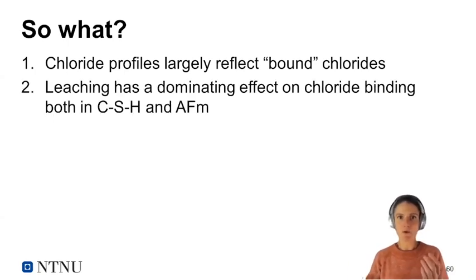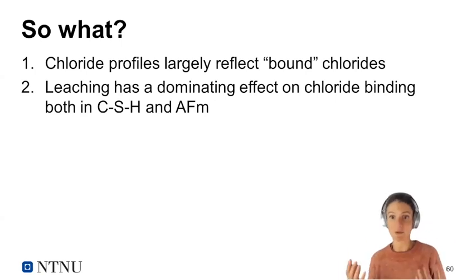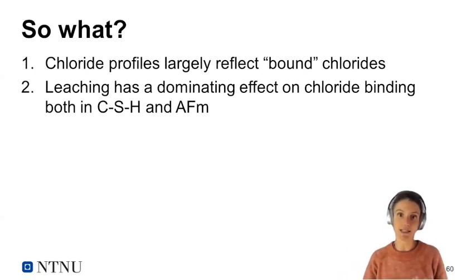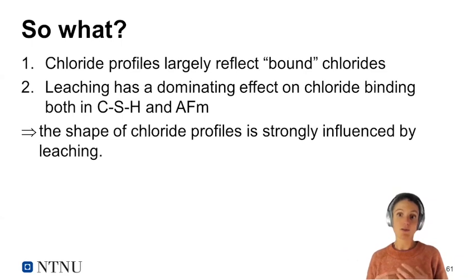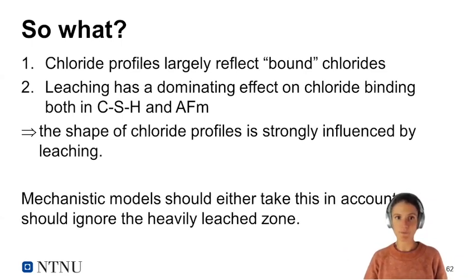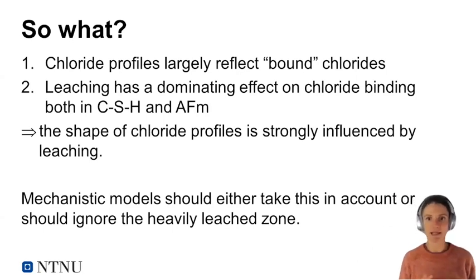Though we've also now seen that chloride binding is really affected by leaching. So both the chloride absorption in the CSH and the chloride in the Friedel salt are strongly affected by leaching. So the shape of the chloride profiles is strongly influenced by leaching. So if we're going to develop mechanistic models or engineering models, they have to account for this.